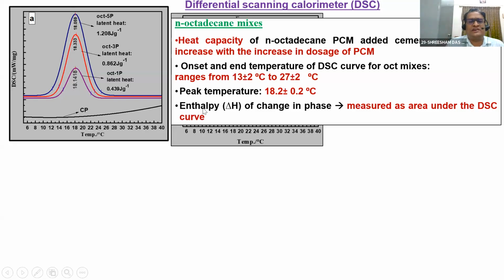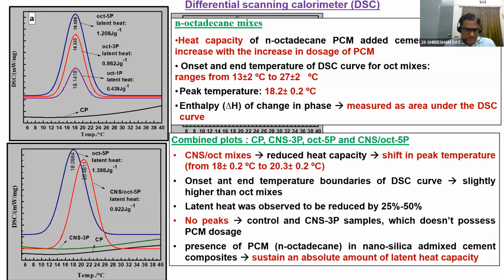So how will I do it? You can measure the enthalpy of phase change, that is measured as the area on the DSC curve. So this is my starting temperature. This is my end temperature where I'm getting a major peak, meaning that is the point where my heat is getting absorbed. So you can measure the enthalpy, that is, you measure the area, and there are so many software packages available which will give you the area if you upload these curves. So that is only the PCM based material.